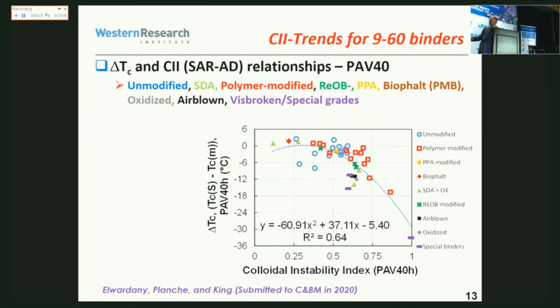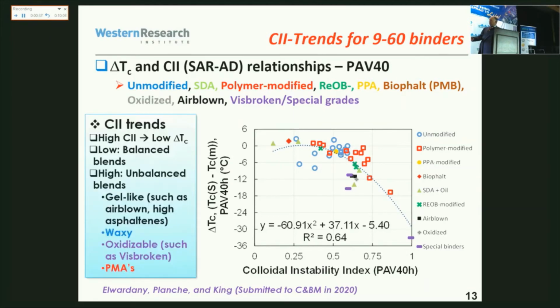And when we look into more detail, what we find is, of course, by definition, the high colloidal instability index binders give low delta TC. So that's kind of the general trend. So this is in agreement with the previous study from Jerry and Andrew. The lower ones are usually what we would call the balanced blend. So this is kind of what we are looking for. But then, what about those guys here? Because now we are breaking world records.